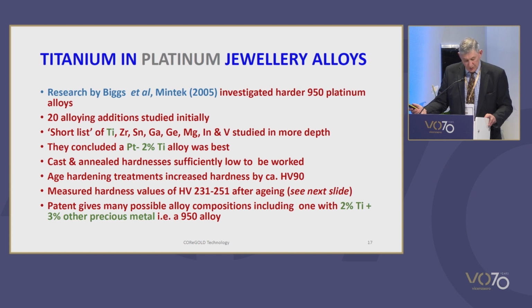From this work, alloys with additions of titanium, zirconium, tin, gallium, germanium, magnesium, indium and vanadium were studied in more depth. This work, along with consideration of other aspects, allowed the conclusion that the best alloy was a platinum 2% titanium alloy. This had cast and annealed hardnesses sufficiently low to be easily worked and formed, but with subsequent heat treatment, the hardness value could be increased by about 90 Vickers.